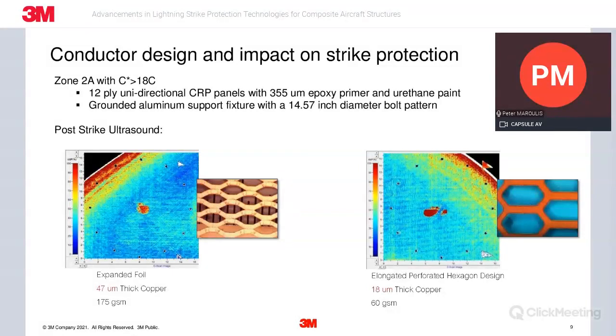So it's important to know that the results here can vary with the thickness of the paint. The higher the thickness, the more charge built up outside of the paint, which then bursts through the paint and attaches to the conductor. This results in more damage. The lower the paint thickness, the less resulting damage, hence why we chose a 355 microns thick primer and top coat system, which is usually at the higher end of what's tested. Next slide.